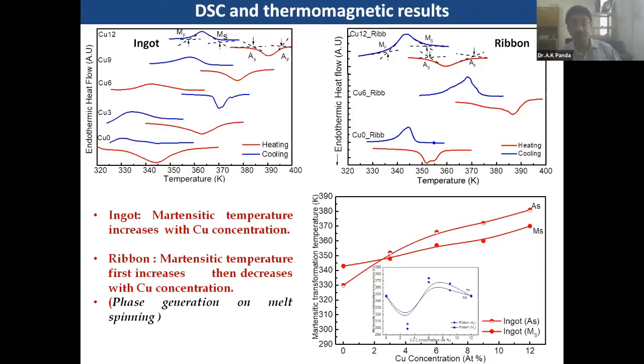So what we learn from here is that martensitic temperature increases with copper concentration, and secondly, in the case of ribbon, martensite temperature first increases then decreases. So in the case of ribbon, you do not get a very consistent trend, because there are two things happening. One is that you are quenching the material, and secondly there is an intermartensite combination. So that is much more complex.